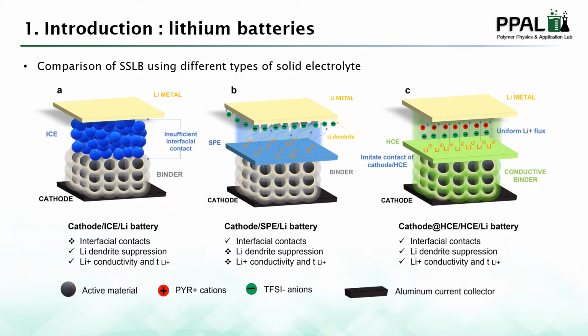And as known, there are generally two types of solid electrolyte, which are inorganic ceramic electrolytes and solid polymer electrolytes. Generally, the inorganic ceramic electrolyte exhibits superior thermal and mechanical performance and excellent lithium conductivities, but poor interfacial contact with the electrode. On the other hand, the solid polymer electrolyte displays high flexibility and good chemical and interfacial stabilities, but relatively low lithium conductivity and lithium transfer number. Consequently, the development of a new type of solid electrolyte balancing the superiority of inorganic ceramic electrolytes and solid polymer electrolytes is a challenging task.